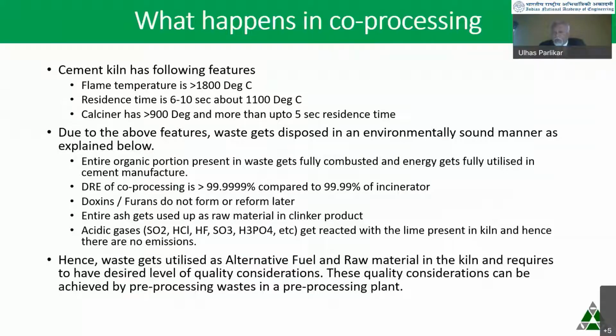And the calciner also has more than 900 degrees centigrade and somewhere around 5 seconds residence time. So under these conditions, when you put any organic combustible material into the kiln, it gets combusted fully. There's a measure which is called destruction and removal efficiency, DRE. For an incinerator to be called the most efficient incinerator, you need 4 nines. That means 99.99% DRE. But there are several kilns where we have done measurements. They range from 6 nines to even more than 10 nines. So that's the efficiency of combustion in the cement kiln.